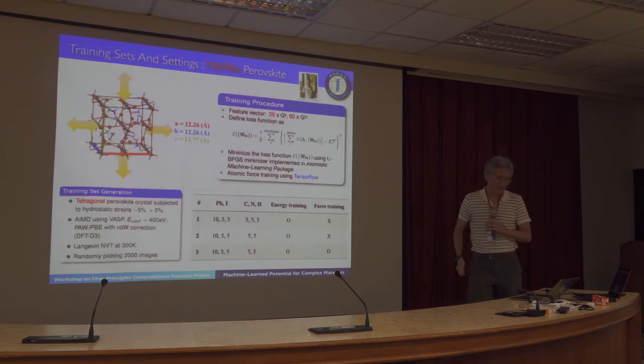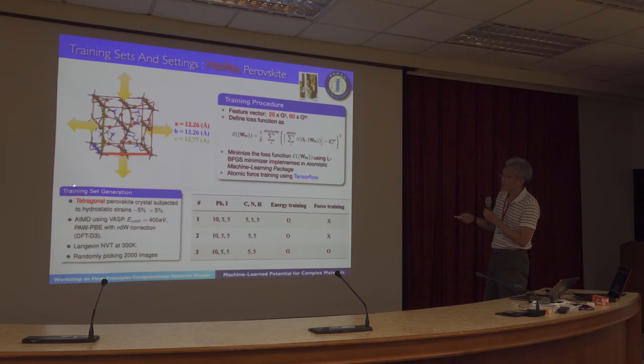Okay, now let's move to the MAPbI3 perovskite material. We start by generating the training set using the tetragonal perovskite crystal, running molecular dynamics simulations at 300K. In order to sample as much of the feature vector space as possible, we also applied hydrostatic strain ranging from -5% to +5%, and we use both energy and force training. Here we tested 3 different training settings, as shown.